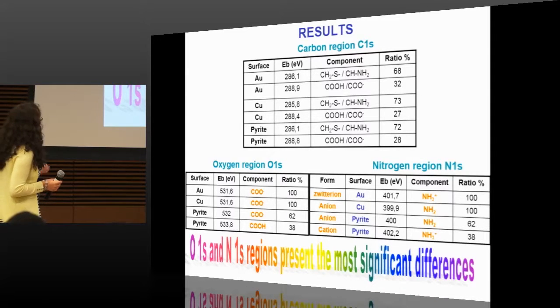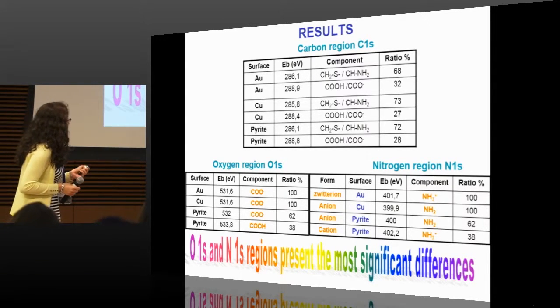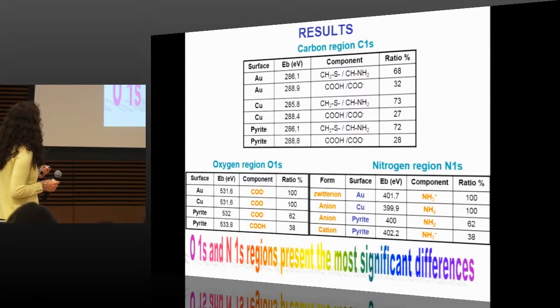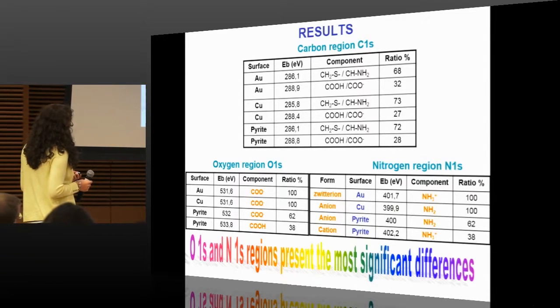Okay, here we have a summary of the binding energy of the different regions, carbon region, oxygen region, and nitrogen region. And the oxygen 1s and nitrogen 1s regions present the most significant difference. With the oxygen and nitrogen regions, I can know about the chemical form of the molecule. For example, I know the amino acid on gold is zwitterionic because I have carboxylate and a protonated amino group.